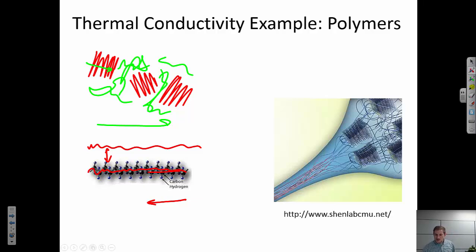So if I could design a way so that my polymers are all lined up so I could get the heat to flow just through that backbone, I could potentially have a polymer which is a really good thermal conductor. And that's not what we think of. Most of the plastics, most of the engineering polymers that we think of are fairly poor thermal conductors. And so there was a group that tried this. They took a polymer and they drew it out to very, very thin, so nanoscale threads, essentially, of these polymers.